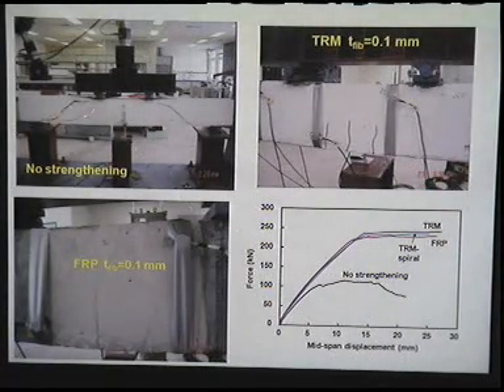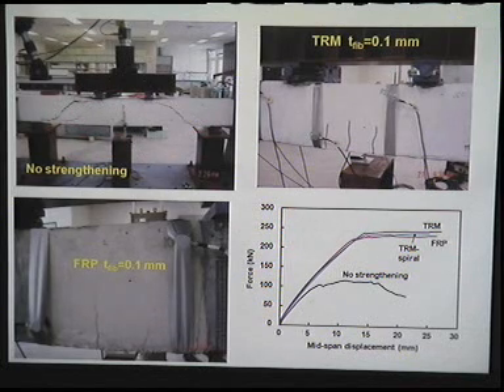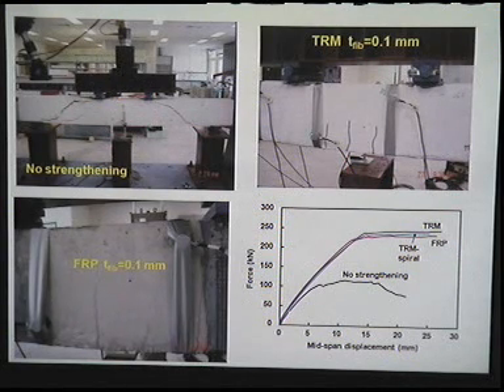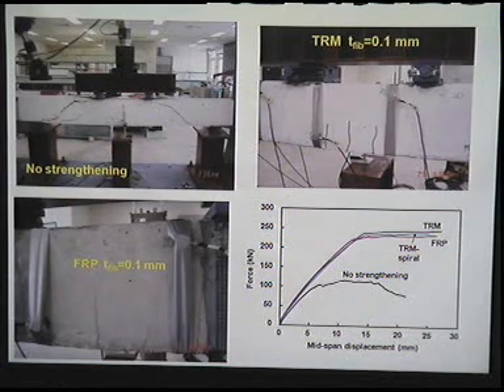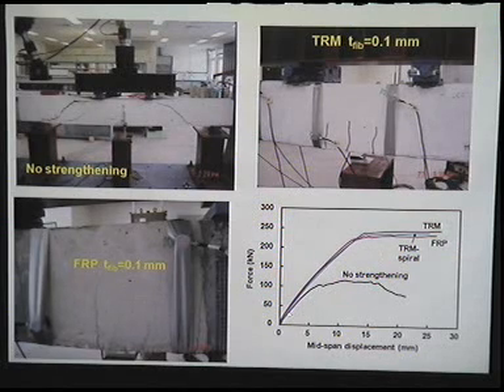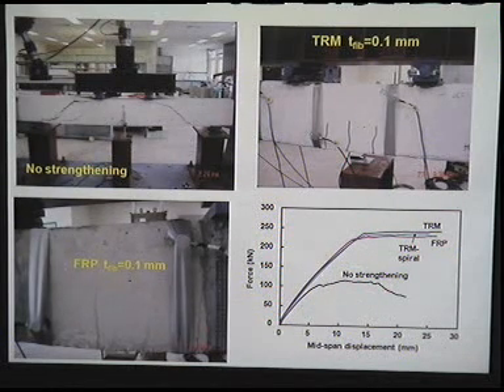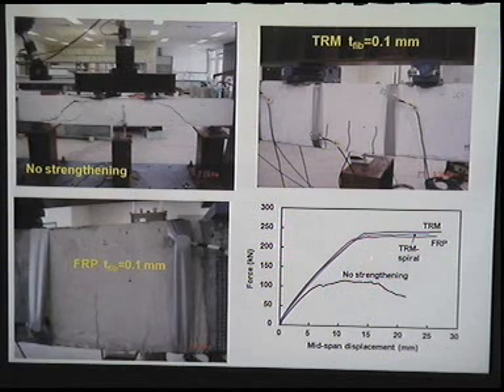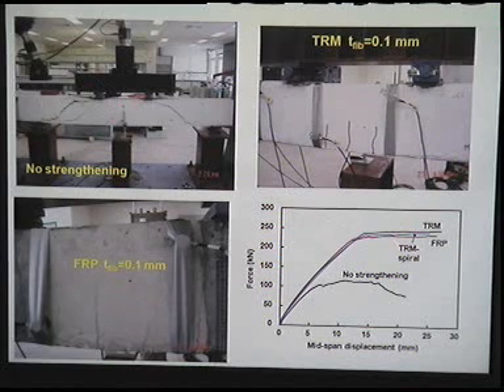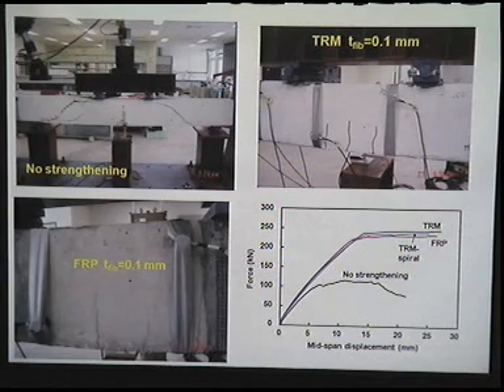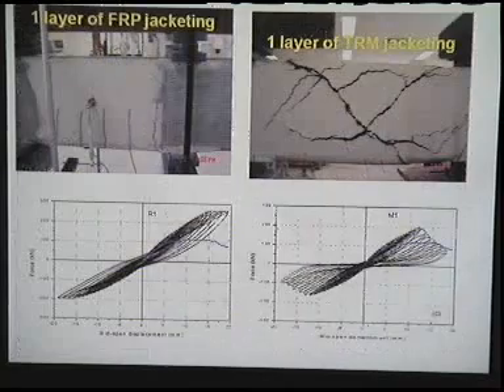You see a typical brittle diagonal shear failure of a beam without any strengthening in the shear span. That's the response in terms of force versus mid-span displacement. This is the response of the member, and how those load versus displacement curves change, and how the failure mechanism changes from brittle shear to ductile flexural when strengthening of those members in the shear spans is done with either FRPs or TRMs. So again, our conclusion here is that the system is equivalent to the well-known FRP system.